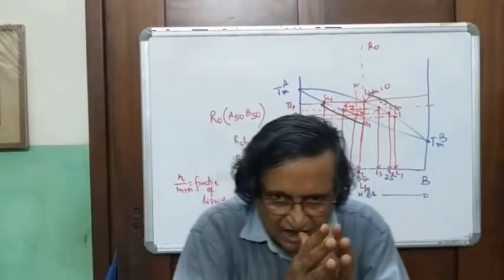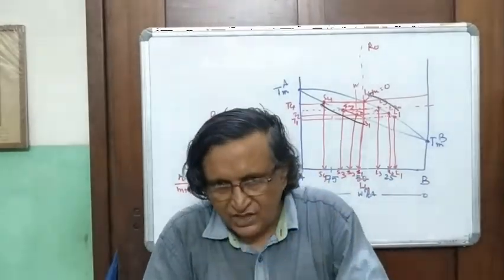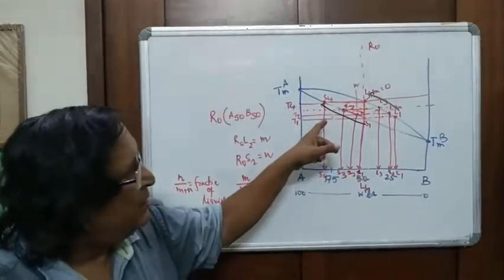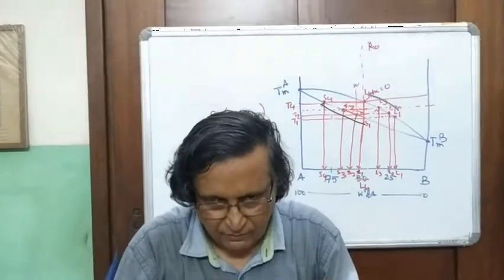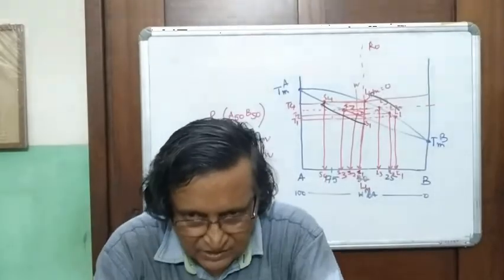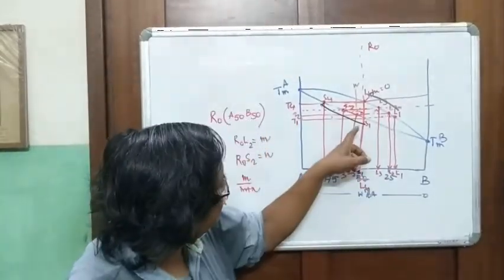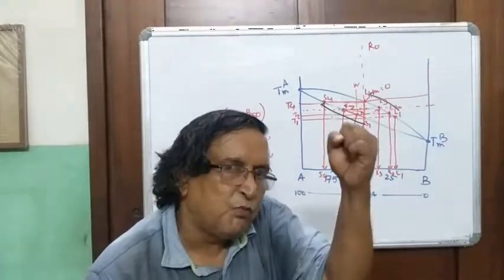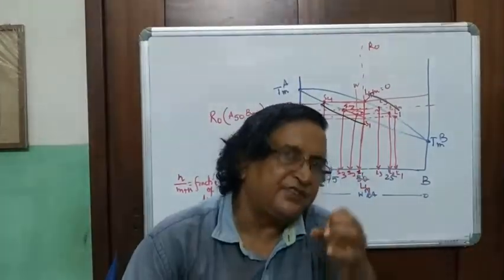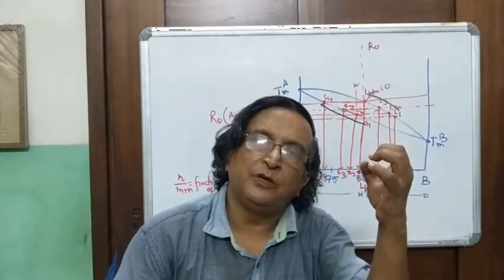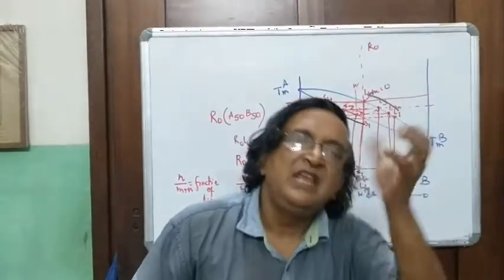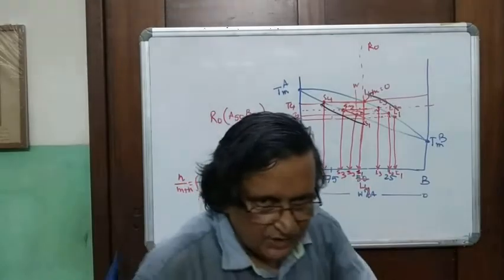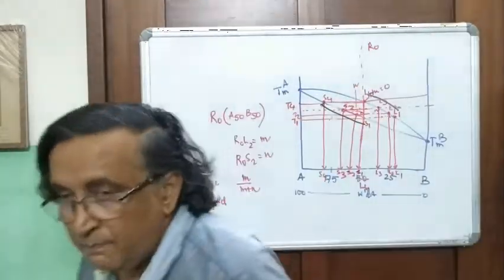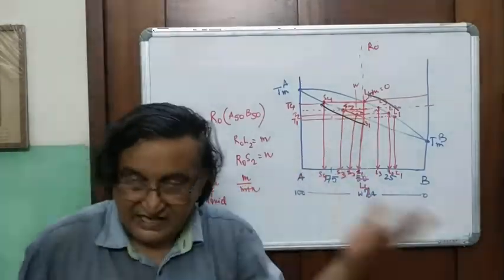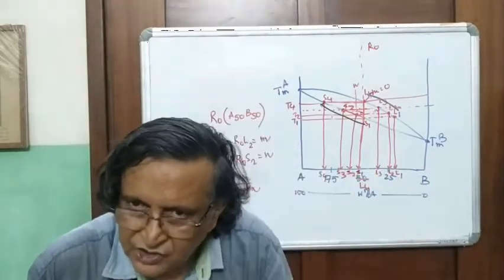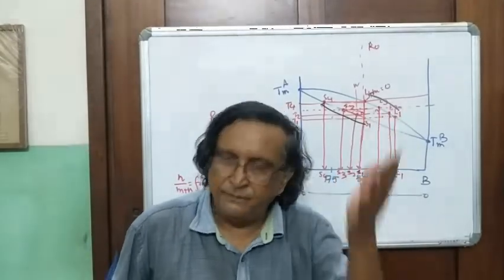Why I'm saying this is that these are the differences between binary eutectic melting involving pure minerals and binary melting involving impure minerals. In impure mineral melting, as you melt the mineral, the low temperature fraction is taken into the melt and the mineral becomes more refractory. That means it becomes enriched in the higher melting temperature component. So if you have to melt the next stage, then you have to heat it a little bit more. If you stop the heating, melting will stop. It will not be possible for the rock to melt anymore, because compared to S1, the mineral S2 has a higher melting temperature. So you have to go on supplying constantly more and more heat for the rock to undergo melting.